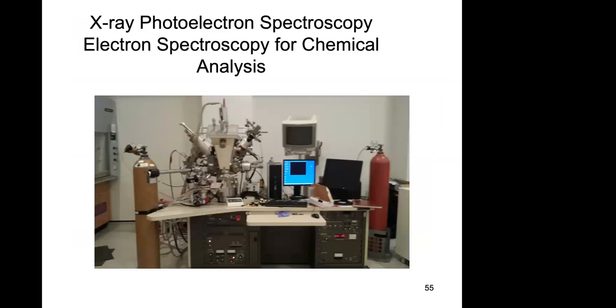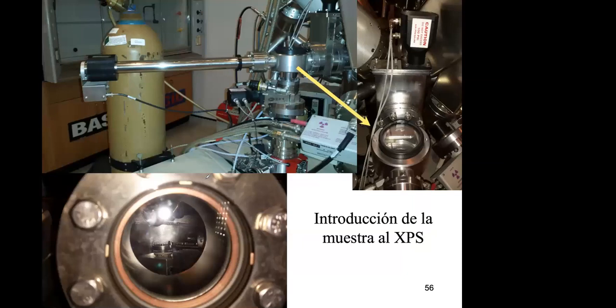So that's a view from the front. This is the antechamber where you put your sample. You remove this lid and you put your sample inside a holder. Then when the vacuum is 10 to the minus 6 torr, you move your rod with your sample and put it inside the chamber. This is the holder for your sample. That holder will click here, and then you remove the rod and your sample will stay here.